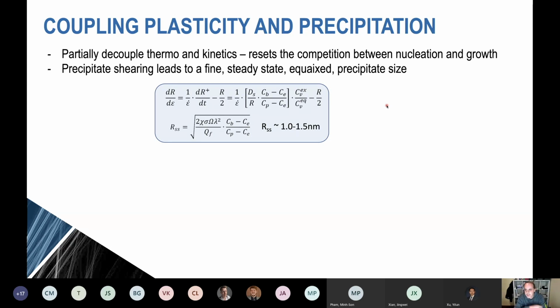And they're equiaxed because the probability of a dislocation intersecting a particle scales with the particle size. And so in a material that, let's say like aluminium, that's FCC, that has a very nice number of slip systems, then this will lead to equiaxed particles. That's quite different from what we see experimentally.